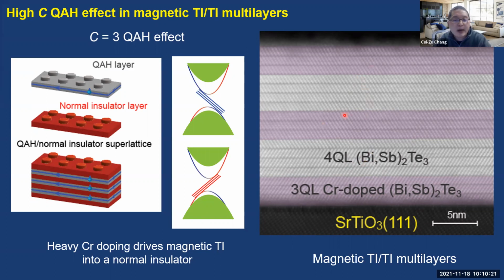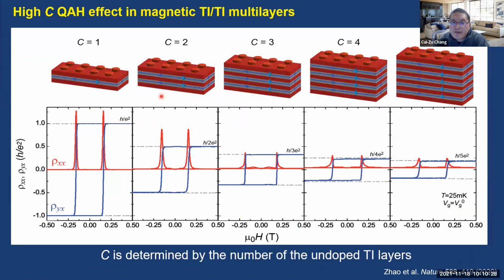And this is the TEM image. We could see the very highly ordered lattice structure here. We fabricated the magnetic TI multilayers with 1 period, 2 periods, up to 5 periods. We performed the transport measurement. We see that the Hall resistance is quantized at h over e squared, and here h over 2e squared, and h over 3e squared up to h over 5e squared. In all these samples, we can see that the longitudinal resistance is vanishing at zero magnetic field.